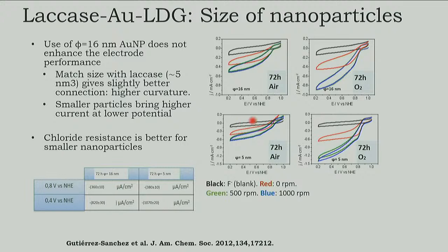So we also compared the nanoparticle size, and the smaller ones, with 5 nanometers, give a much better current than the ones that are 16 nanometers. This is because the size of the enzymes is mostly the same as these small nanoparticles of 5 nanometers. They have a much bigger curvature, so 16 nanometers starts to be similar to a flat electrode from the point of view of a small enzyme. For us, it's a nanoparticle, but for enzymes, they don't see so much curvature, so they start to behave similar to a gold electrode.